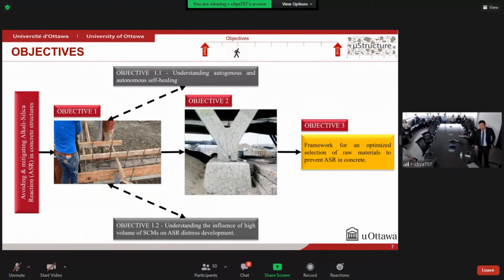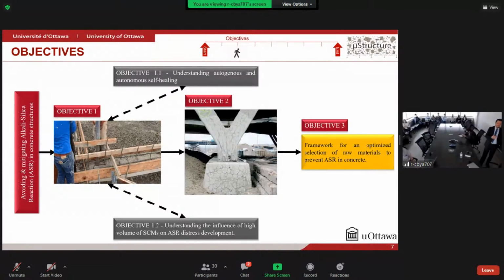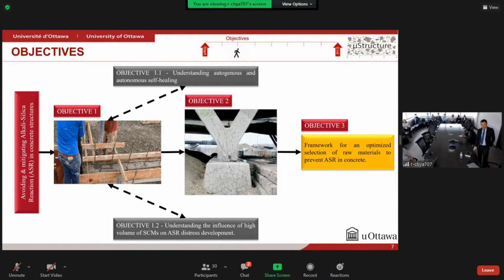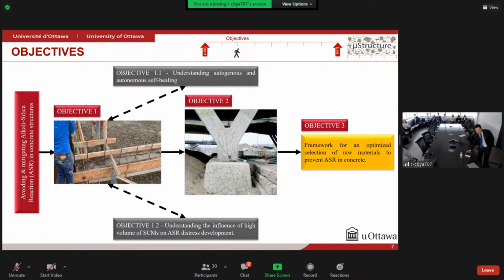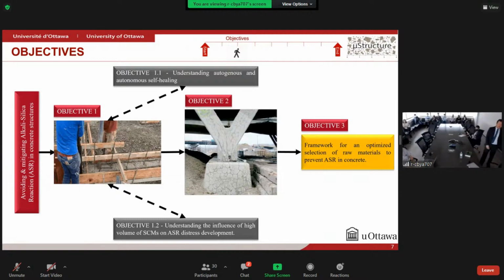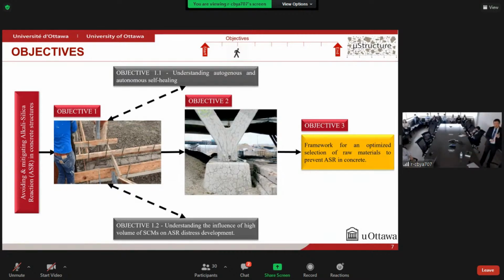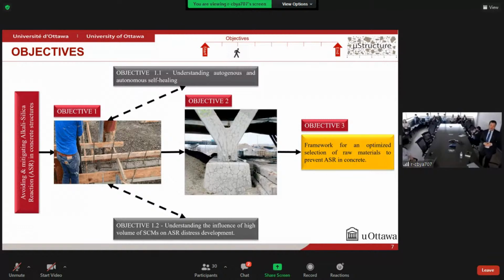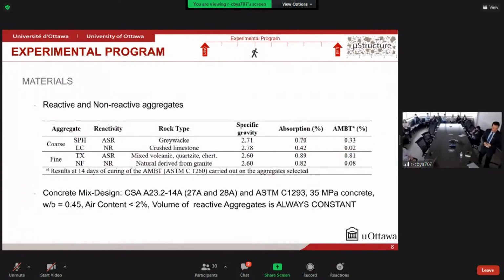Also, I would like to mention that we developed two parallel research here to first understand autogenous and autonomous self-healing of concrete, and then the influence of high volume of SCMs on ASR distress development. We used two different reactive aggregates, a greywacke reactive coarse and a natural fine reactive aggregate. The overall concrete mix design are based on the most used standards in North America. And it's important to mention here that the volume of reactive aggregate is always constant for all mixtures.